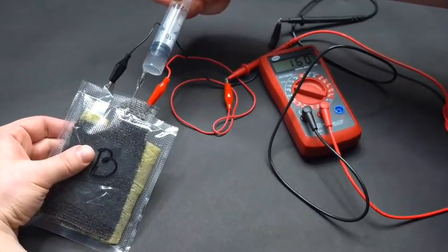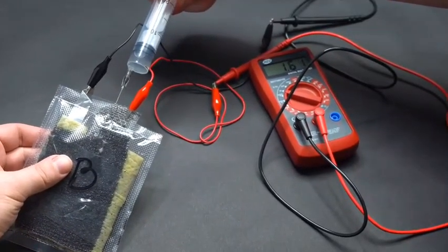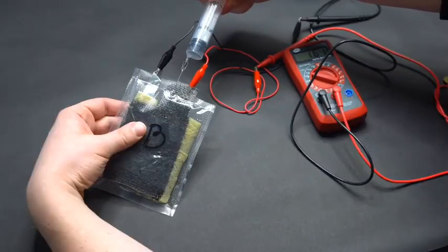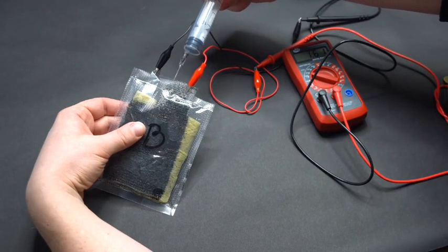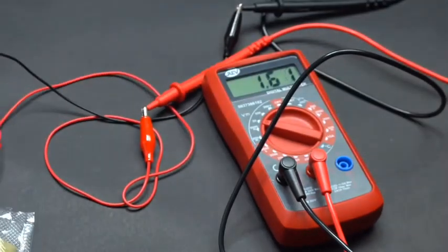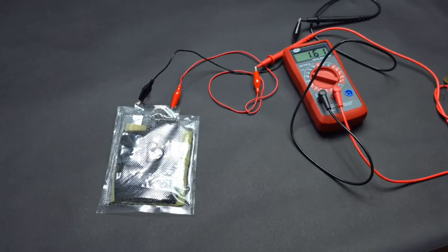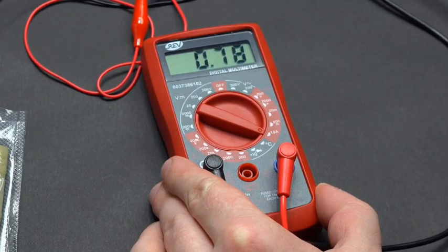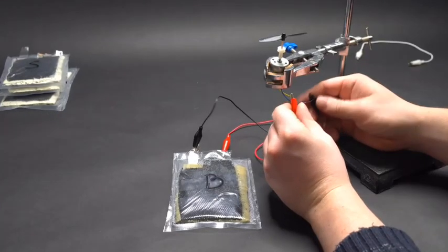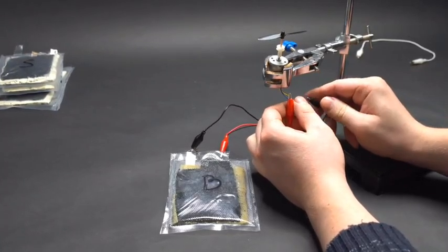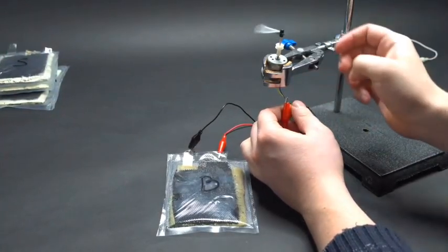Now we can see how the multimeter immediately shows a rapid increase of voltage. Now the sodium hydroxide has removed the protective layer from the foil, and the voltage has increased to 1.6 volts, which is quite a good result, although amperage isn't very high, just 0.75 amperes. This voltage is enough to supply a small electric motor at low revolutions.